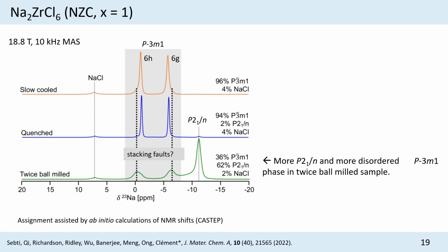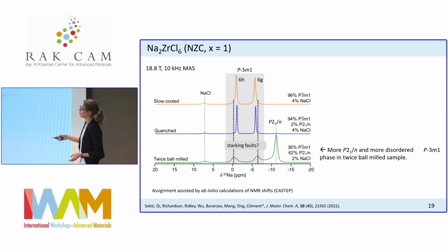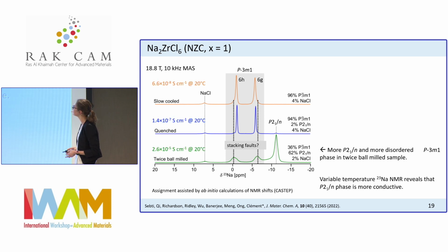If you now look at the broadening of the peaks for the P-bar-3m1 phase, you see that they're much broader in the twice-ball-milled sample, which may not be surprising. We're basically making a much more disordered version of this P-bar-3m1 phase. We believe that there are some stacking faults too that are induced by this ball milling process, because we've seen this in other related systems.